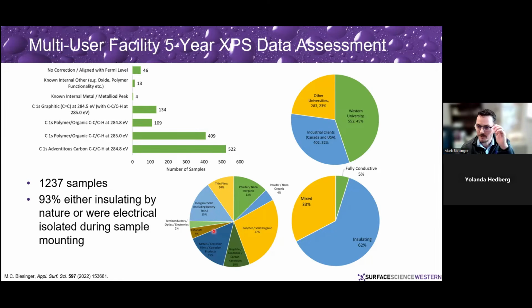Lots of different types of materials that we looked at. And then we looked at, well, what, 62% were insulating by nature. About 33% were a mix, so they had insulating properties and conductive properties. Only about 5% of the samples that we looked at were fully conductive in nature. So that's a small amount that's available for that type of analysis.